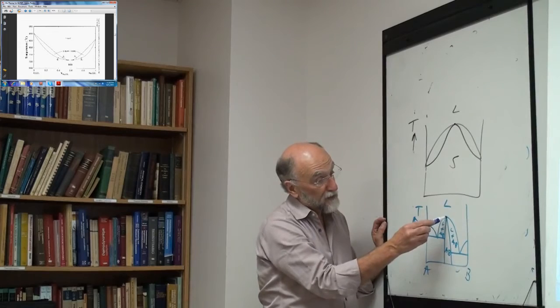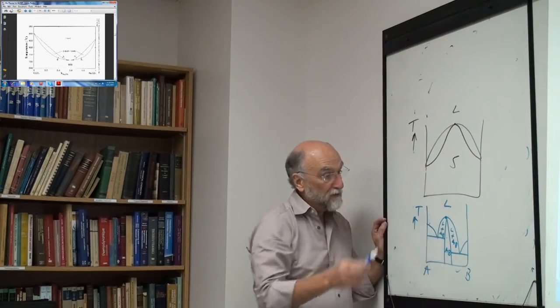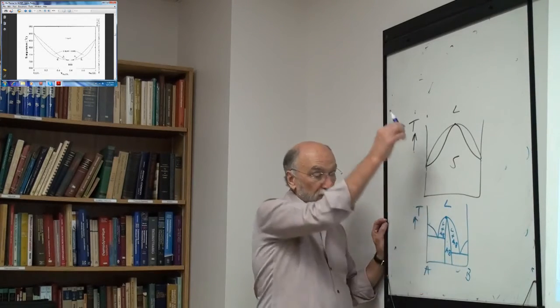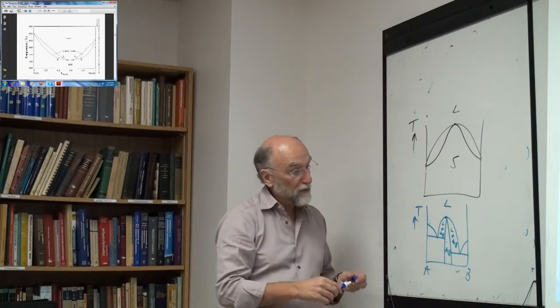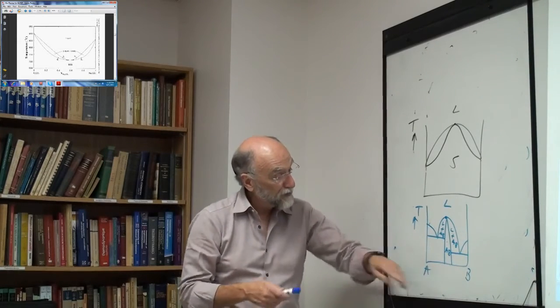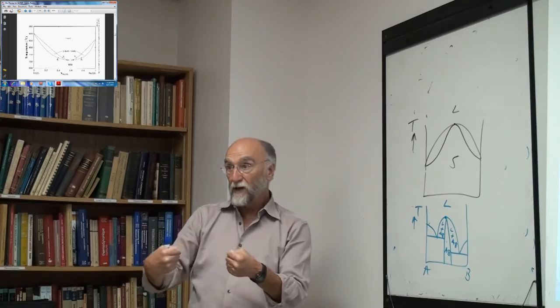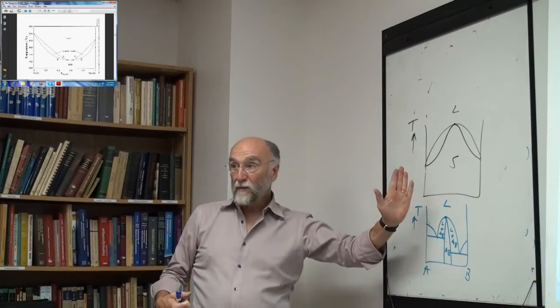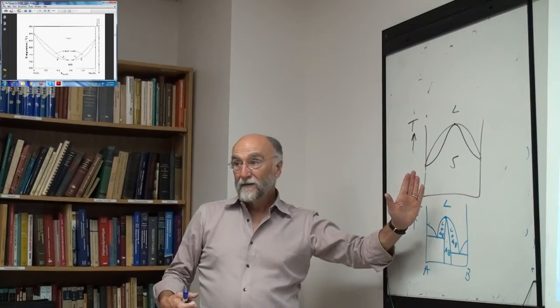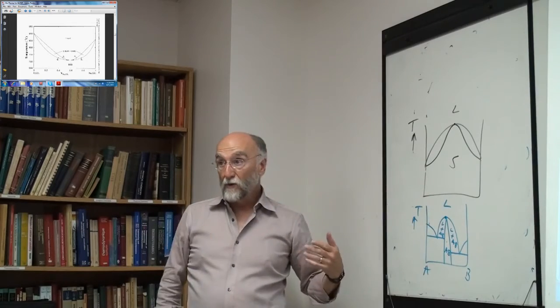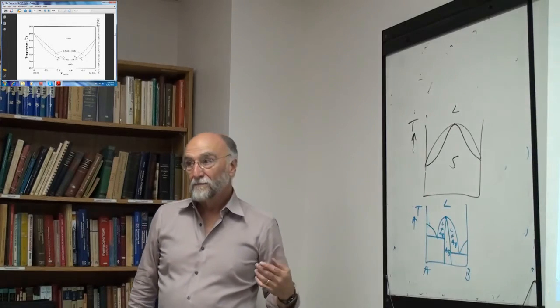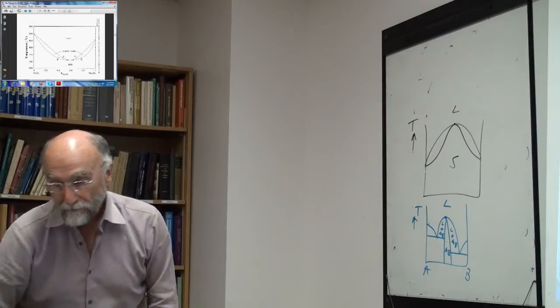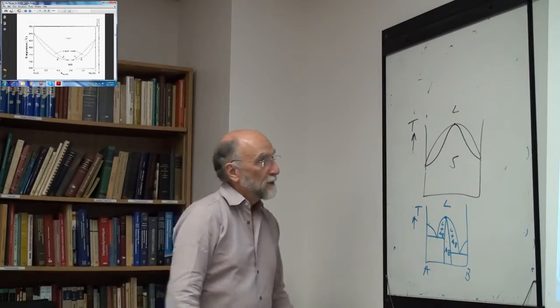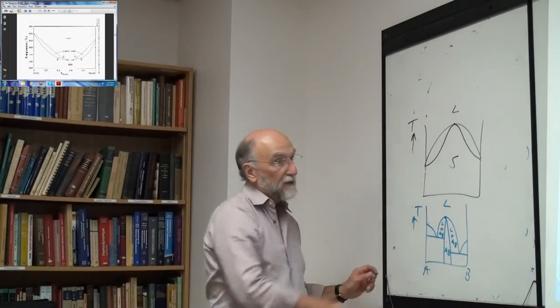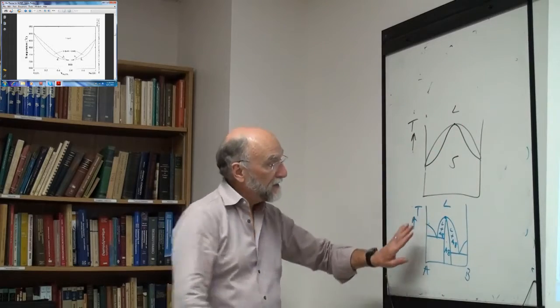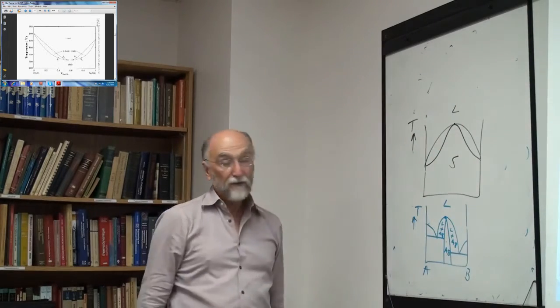So this definitely means now that the solid is stabilized relative to the liquid. It's made the solid more stable because the solid has become ordered. It's formed an AB solution with very strong AB bonds, which has stabilized it enthalpically relative to the liquid, which is more randomly mixed. But this maximum here and this minimum here, thermodynamically, they describe the same thing: intersection of the Gibbs energy curves.